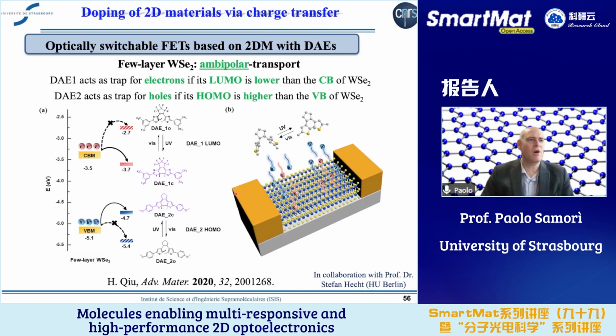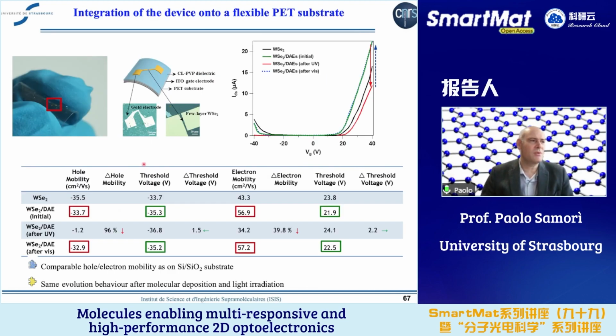And so we physisorb on top of the tungsten diselenide a blend of the two diarylethenes. And without going into details, you can see that at the same time, by illumination with UV light, we can reduce drastically the hole mobility by 96% and the electron mobility by 40%. And then with visible light, we recover all of them by going back to the open state of the diarylethene, both for both types of diarylethene, the one that controls the hole mobility and the one that controls the electron mobility.